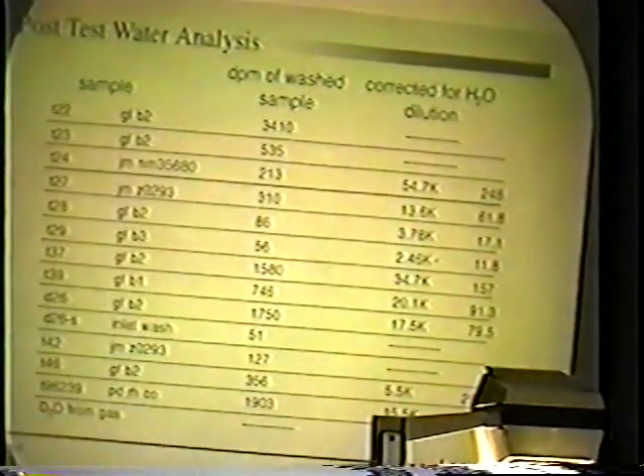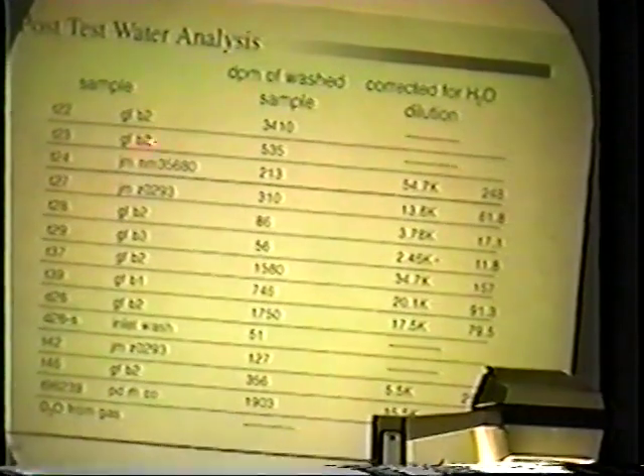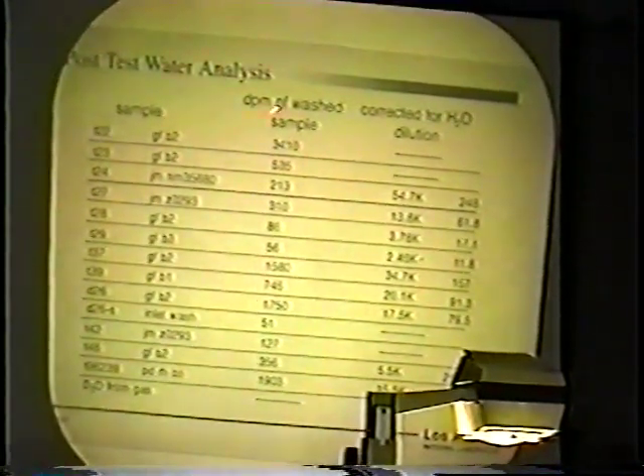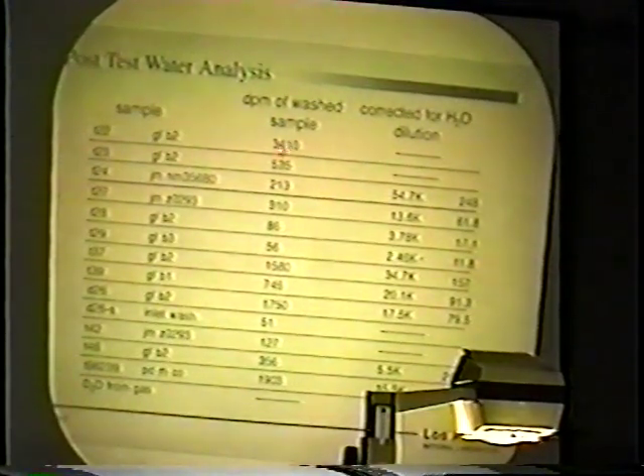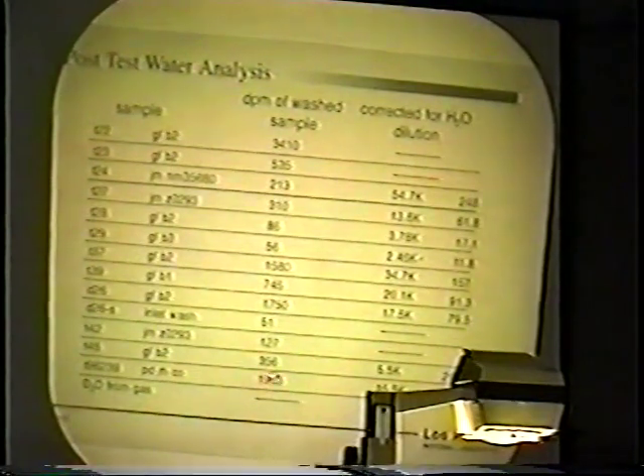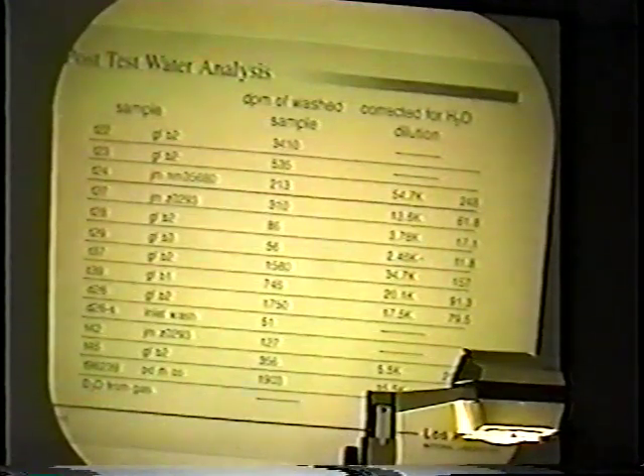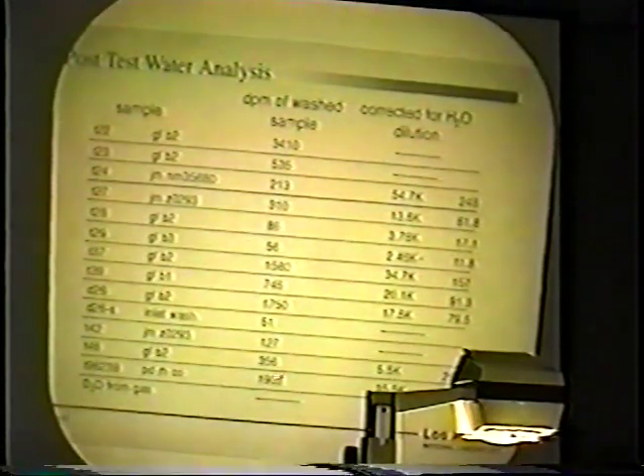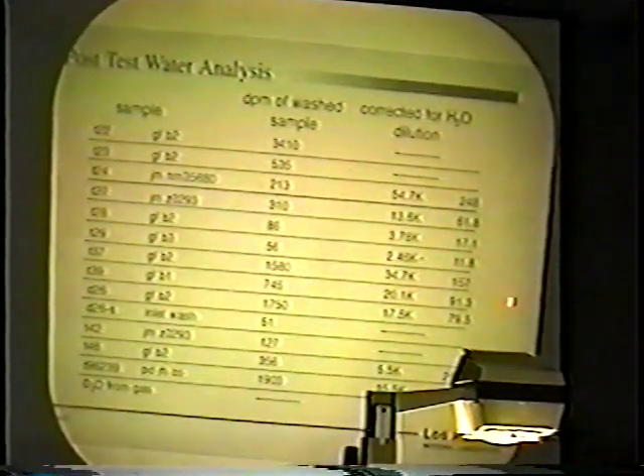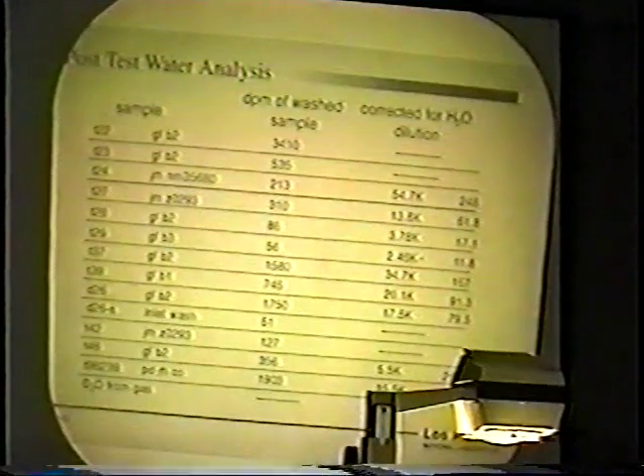A couple of the other things that we do: after the loop's been run, we'll wash the cold trap out if we put any CO2 in. So these are CO2 runs, and we'll look at the counted sample. This is the D2O combined from the gas. It has about 220 ppm in it. These are the samples corrected for the water dilution. This is the raw data. This is corrected for water dilution. This is sort of the enhancement over this 220. So what we expect to see is 220 ppm, and what we're getting is these values.